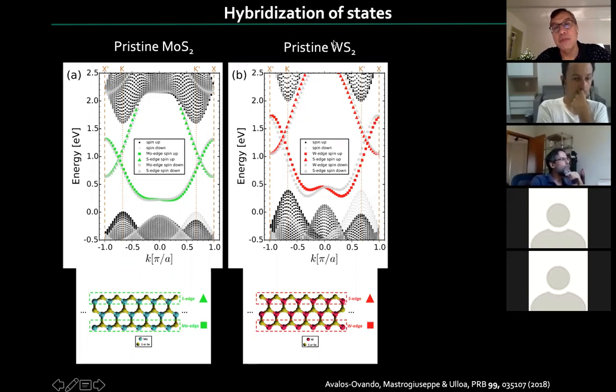Now for the tungsten disulfide, you have a similar structure. Notice here that the spin orbit coupling is stronger, so the gray triangles are further away from the red, but again it has a similar sort of structure. Notice the dispersion is rather asymmetric because of this spin orbit coupling. All the states are of course time reversal symmetric, as they should be.